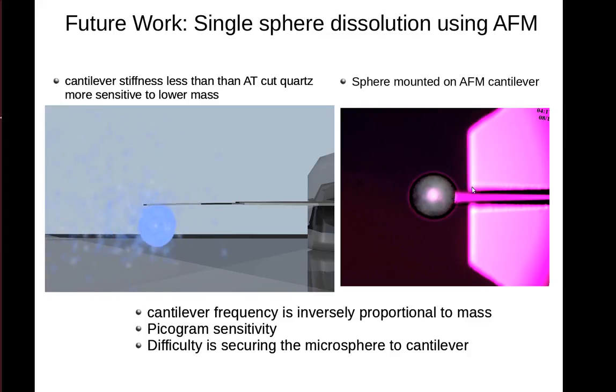On the right, we see an actual photograph image of a microsphere mounted to a cantilever. The problem currently is keeping the microsphere attached to the cantilever during the entire measurement. It is interesting that the sensitivity estimated for the cantilever technique will be on the order of picograms, and some papers report femtograms, therefore giving several orders of magnitude increase in sensitivity over the QCM.